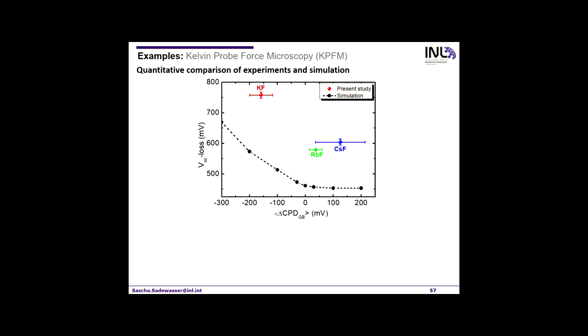And then here we have rubidium and cesium. You can see here the best efficiency in this case was the rubidium one, not the cesium one. So now we can use the information from our simulations. We can look at the open circuit voltage, and we know what the gap is, and we can calculate the loss in open circuit voltage for each of these band bendings here. And this is plotted here as this line.